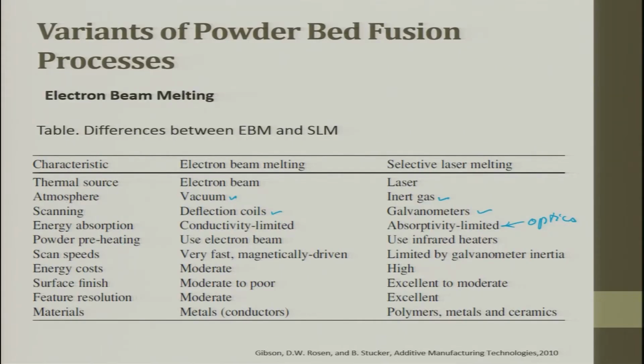Then preheating: with electron beam it can be done, while infrared can be used to avoid contamination from the free atmosphere getting mixed. Scanning speed is very fast in electron beam, it is limited in laser. Because the deflection coil is used, it can scan at very high speeds. The energy cost is moderate, it is very high. Surface finish is moderate to poor, it is excellent to moderate. The feature resolution is moderate in electron beam, excellent in selective laser melting. Materials, it can be used for metals, it can be used for any metals and non-metals.